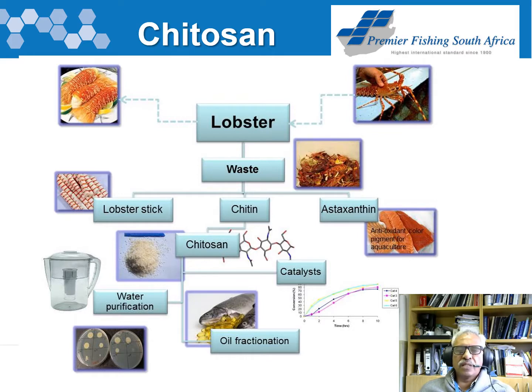to produce what we call a lobster stick, and the residual chitin itself can also be extracted with organic solvent to give that orangey reddish color, which is actually a pigment called astaxanthin. So it's got very good antioxidant properties. Then the chitin is deacetylated to chitosan, and we've done some work in producing catalysts; chitosan is a solid support catalyst. We've done some oil fractionation using chitosan, water purification, and antimicrobial studies.